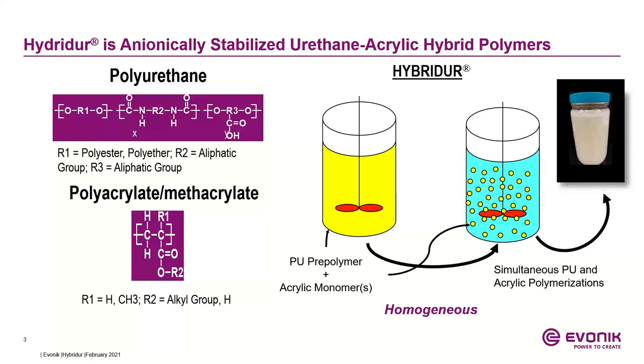the binder. One possible reason for this behavior is that, at the molecular level, the acrylic polymers are not as soluble in the polyurethane polymers. Therefore, the polymers remain phase separated during film formation, which is partly responsible for the diminished performance of polyurethane acrylic blends. In order to take advantage of the potential cost reduction afforded by the acrylics and maintain a greater share of the polyurethane dispersion properties, Hybridur acrylic urethane dispersions were developed.